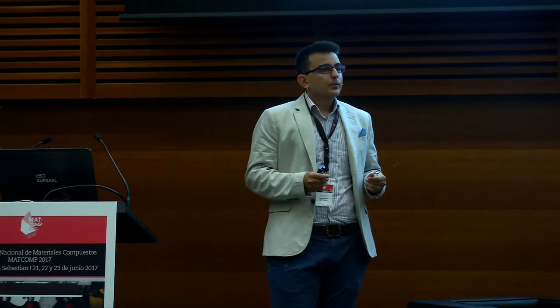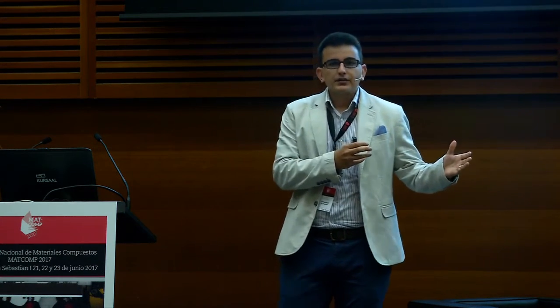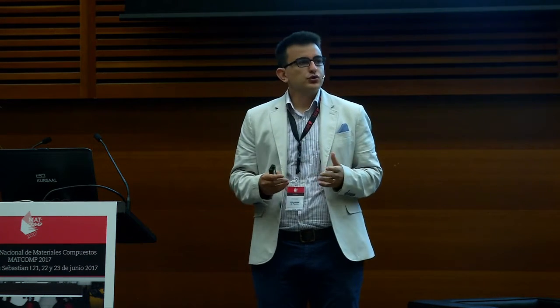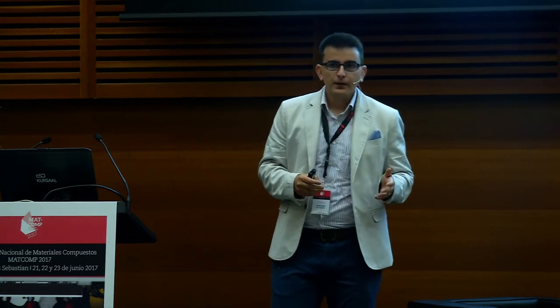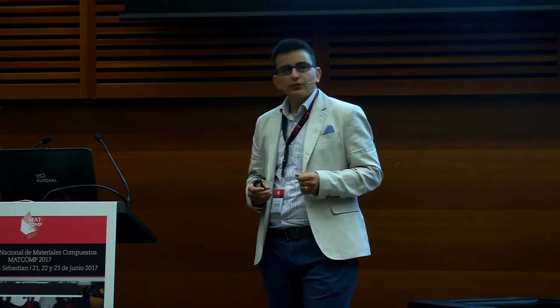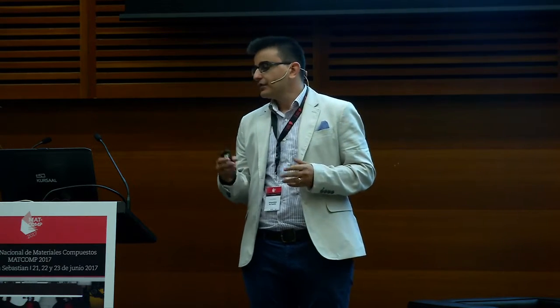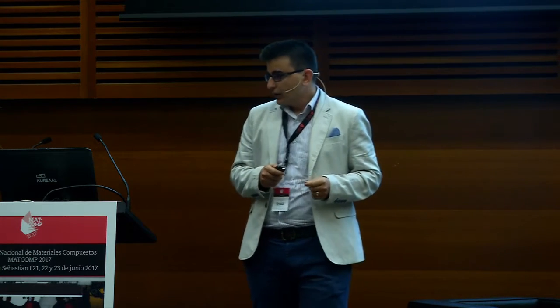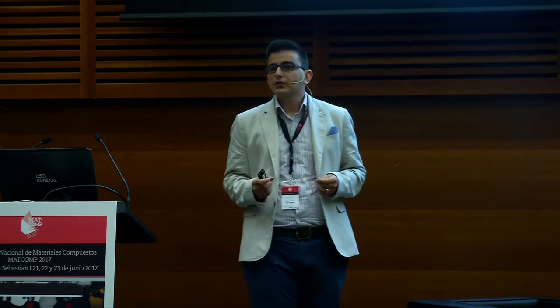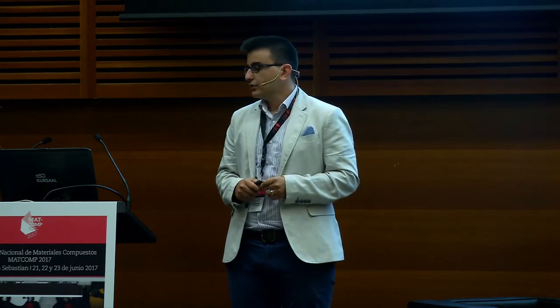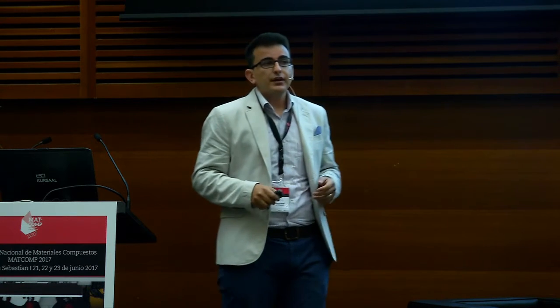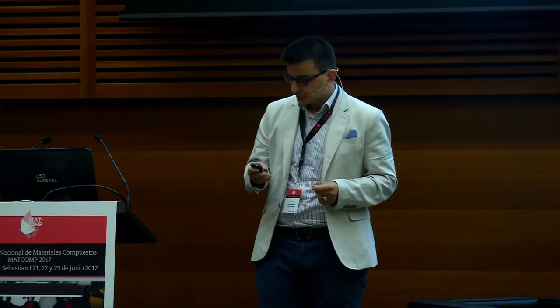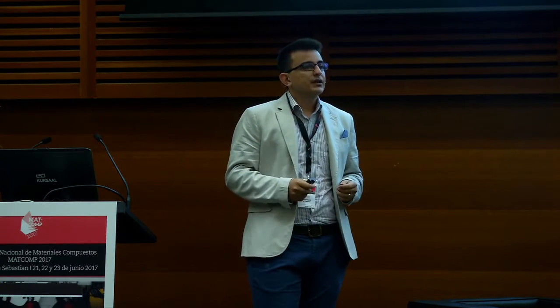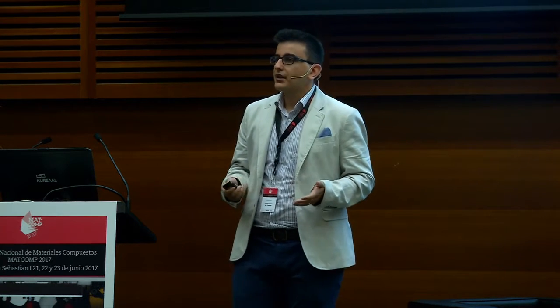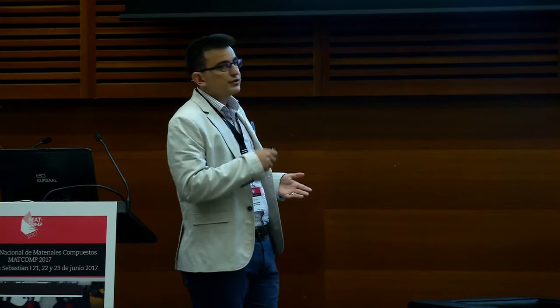And the question is, it's obvious that there's a direct influence of this lifeline on the mechanical performance during the service life applications. So here I have an example of changing the failure mechanism of a composite material. Here we have a simple short beam shear specimen in a 3-point bending loading condition, and we have a matrix crack and a small porosity in the specimen. So after performing some simple tests, some of the groups actually failed in tensile mode with 750 newtons force at fracture.